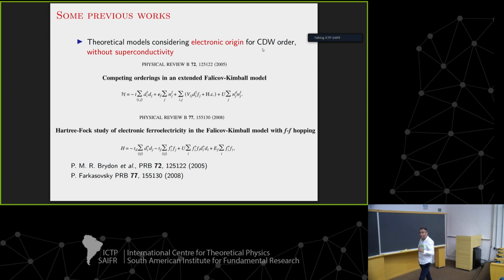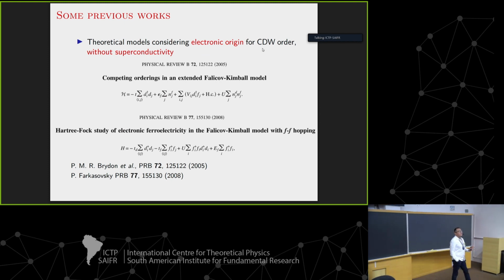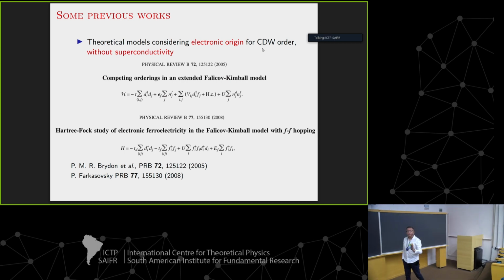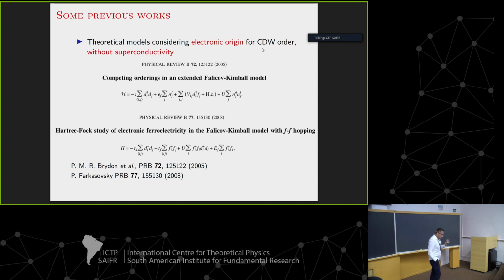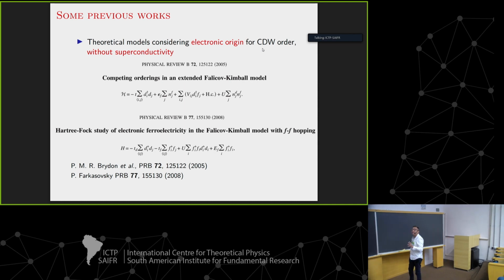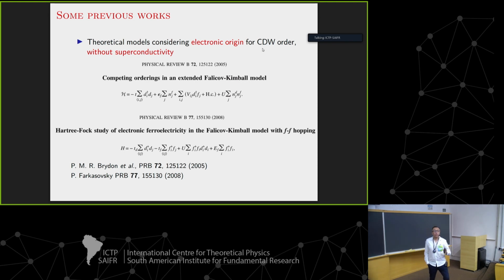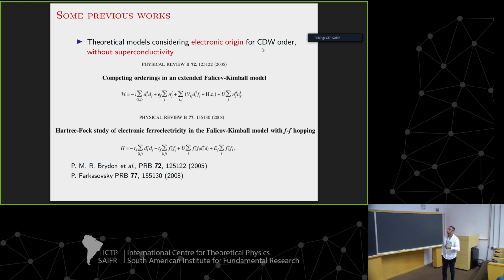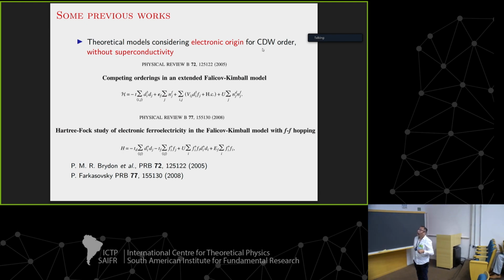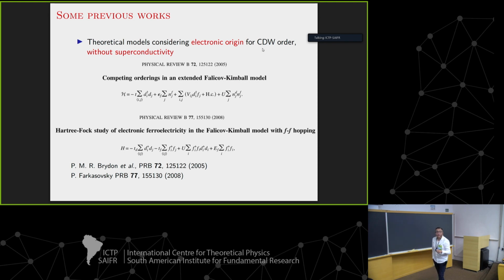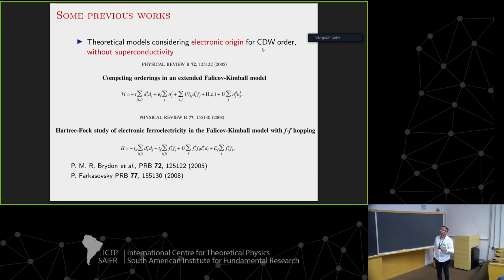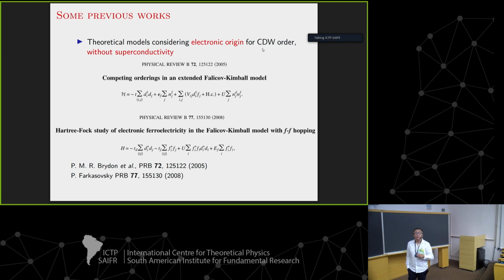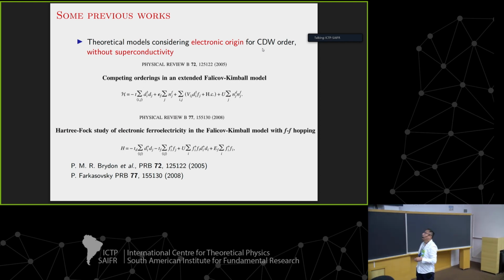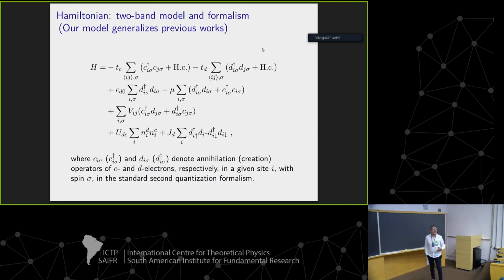As I said before, charge density order was initially proposed as coming from the electron-phonon interaction. But this charge density order can also come from the electron-electron interaction, mainly from the Coulomb repulsion, as was reported, for instance, in these two papers here. These papers have a two-band model on a square lattice, where they consider that the charge density wave appears from this local Coulomb repulsion here, but without considering superconductivity. But now we are going to generalize this model.